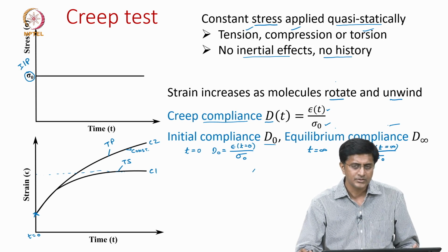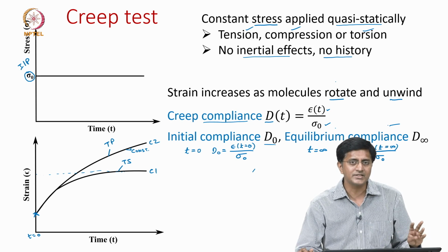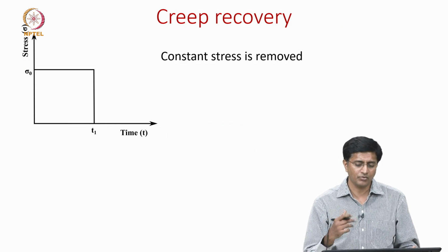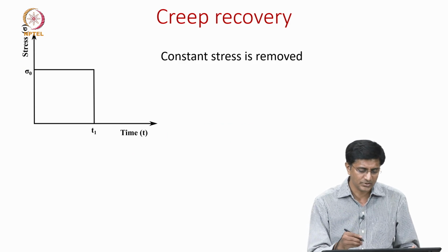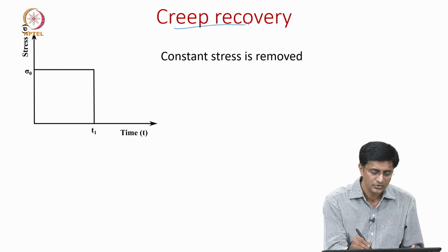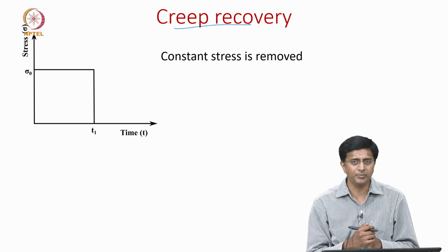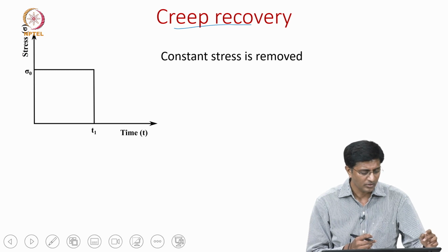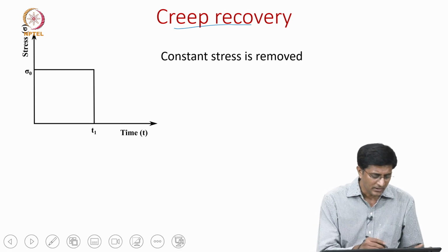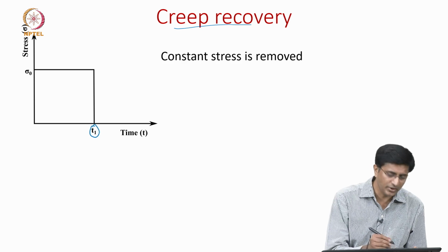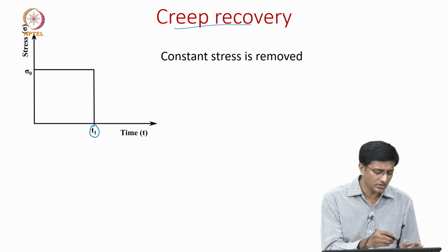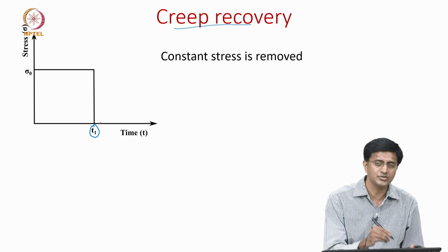Now that we have looked into the relaxation test and the creep test, there is another test which is commonly used, called creep recovery. It is very close to the creep test, because like in the creep test you apply a constant load, but the only difference is, let us say around time t equal to t1, after a while you remove the load. So the load goes back to 0.